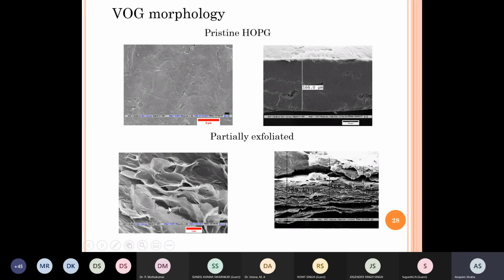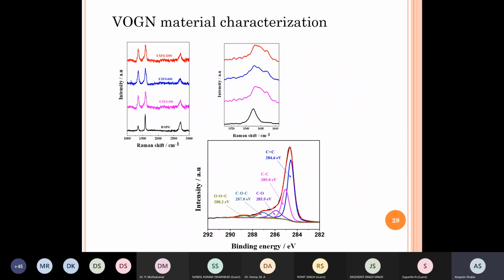And during the process, not only do these flakes come out from the top surface, but this is what happens in a cross view. You see that the layers also get partially delaminated, and there is a lot of open space created between the graphene layers, which is not visible in the previous before exfoliation of the pristine electrode. So both of these increase the surface area and therefore improve the capacitance.